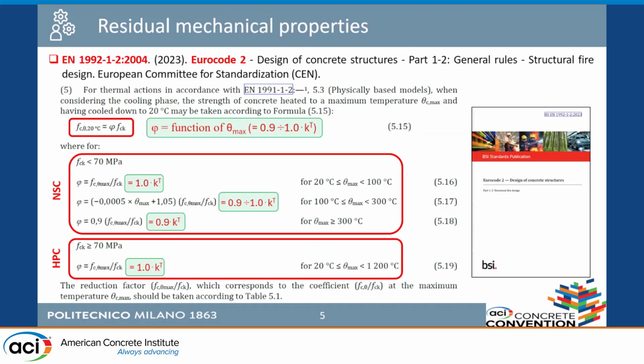The EC2, here it's wrong because it's written 2004, but this is the last Eurocode, so 2023. And for the first time, Eurocode tries also to give the information for what's happening in the residual condition, because during the cooling down of the temperature, we have a further increase, not so much, but a further increase of the damage because of the relaxation of the irreversible strain accumulated during heating, and so we have further microcracking.